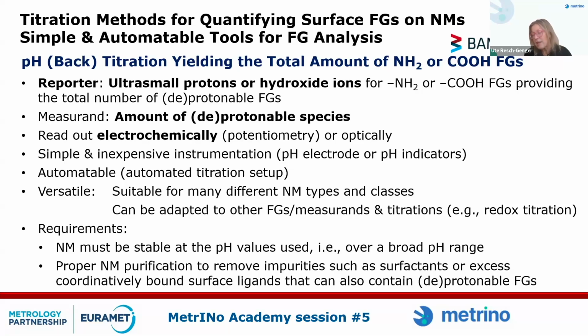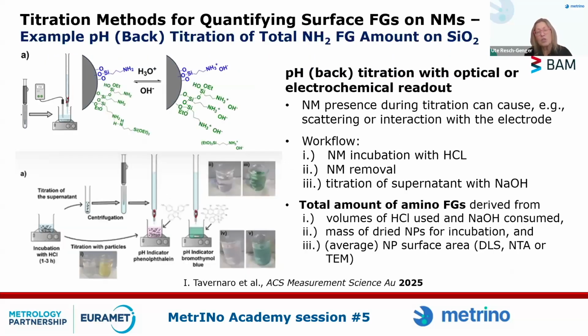It is suitable for many nanoparticles, and it can be adapted to other functional groups. Redox titration, for instance. A requirement is that the nanomaterial must be stable at the pH values used, and you need to make sure that you can remove impurities like surfactants, excess coordinative bound surface ligand, something like this, because they also often contain deprotonable functional groups, which would otherwise mess up your assay results. So this is how you do this.